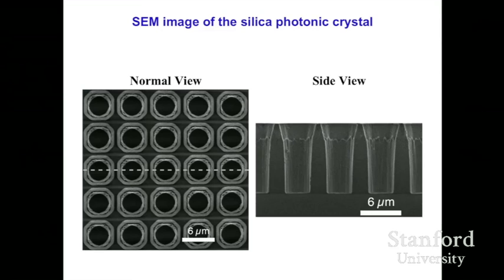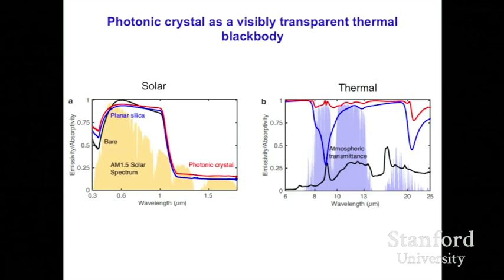This is the SEM image of the silica photonic crystal. It has a square array of air holes etched into silica. The periodicity here is on the order of 6 micron because this has to match with the thermal radiation wavelengths around 10 micron or so. So these are some of the optical and thermal spectral properties of these structures.